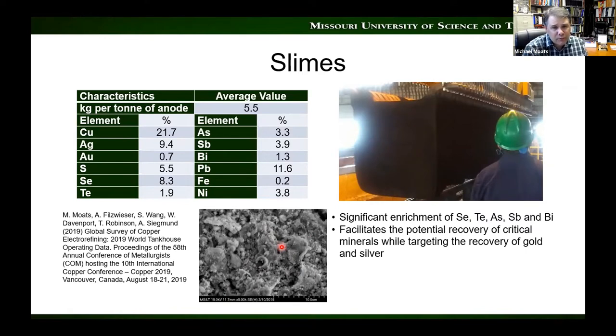And you can see here from the same survey that we did in 2019 that for every ton of anode that we produce, we get about 5.5 kilograms of slimes. Those slimes, again, have a lot of copper, but you'll see that we have a lot of silver and a lot of gold. We have 9 weight percent silver and almost 1 weight percent gold. So obviously the value in slimes is in gold and silver. But there's a lot of selenium, tellurium, arsenic, antimony, bismuth. Now we're talking weight percents. So again, we've had another concentration factor of another 10 or 15. And so now these slimes are ripe for processing, not only to recover the silver and the gold, but potentially for these other critical elements as well.